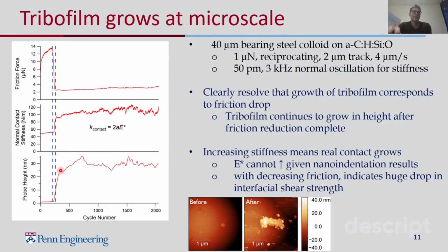Additionally, the probe height goes up. And the reason this happens is because we are in load control. So if something grows in between the two sliding surfaces, the tip has to move up to maintain the same normal load. And so that's what we see here.